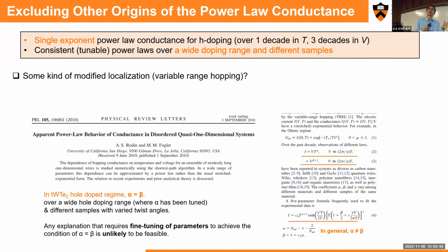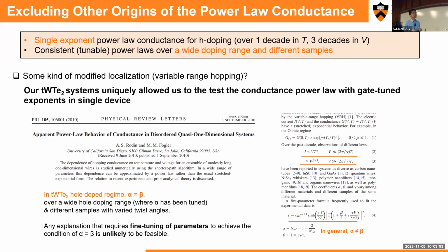So the temperature dependence and the external bias dependence always have the same Luttinger liquid number, or power law number. And so we think that it's unlikely to be feasible to really reach such an alpha equal to beta, but this is the case in our system. And we can keep changing the gating, just like changing the disorder density or the system's density. We can keep seeing this alpha equals beta is always there.